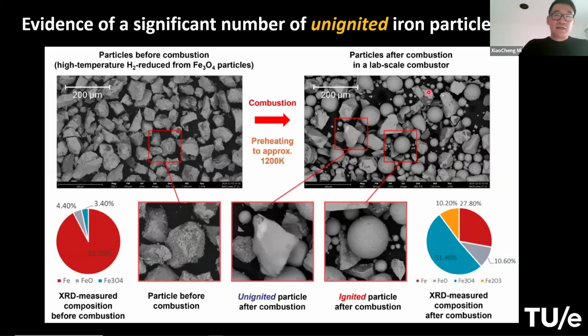This means that in these combusted particles, there is still a large portion of them that fail to be ignited, because they look irregular. They have never been into liquid phase. And this is consistent with the X-ray diffraction measurement. You see a lot of irregular particles, and indeed, you see there is still a large portion of iron remaining in the product particles.